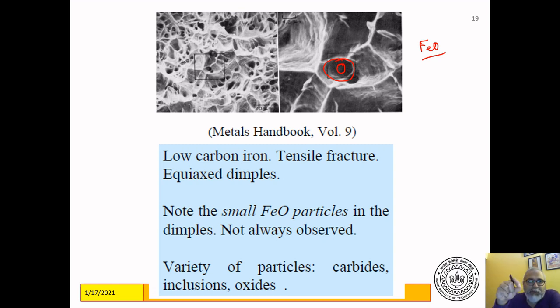So while you are improving its properties by adding these second phase particles, improving corrosion resistance and so on and so forth, you are also making it susceptible to formation of these dimples, which can then coalesce to form a bigger void, and then that void can grow catastrophically and lead to failure. So you are improving certain properties by adding these second phase particles, but you are also subjecting the material to the risk of failure by crack propagation. And these can be different kinds of things.